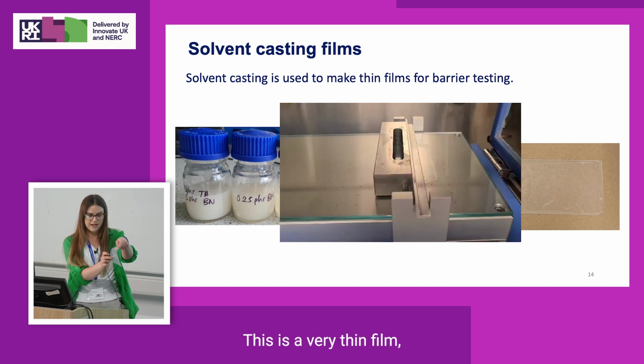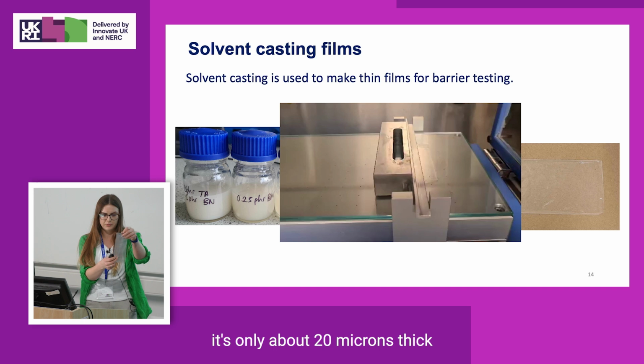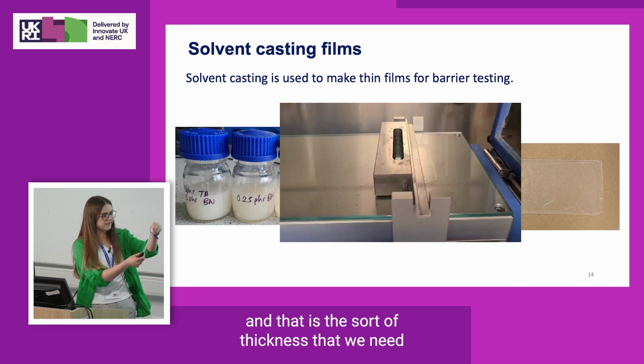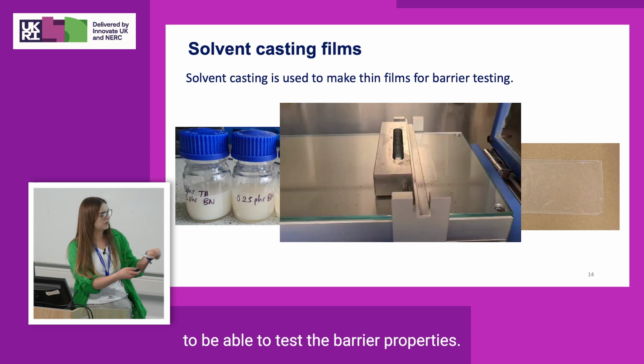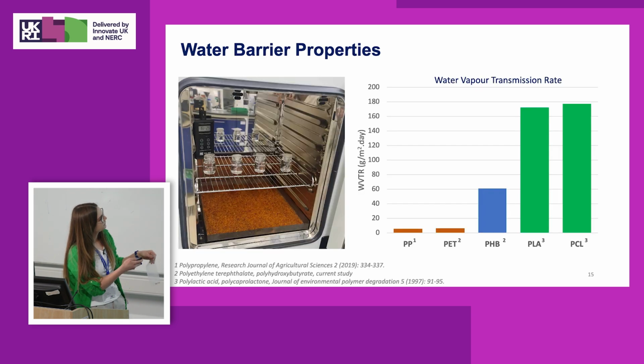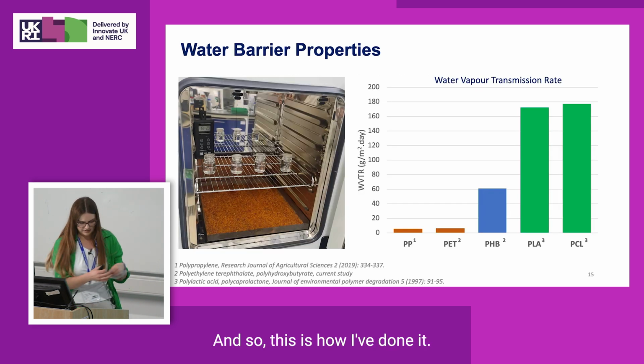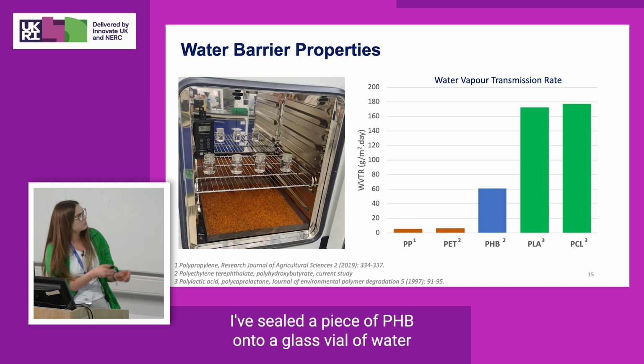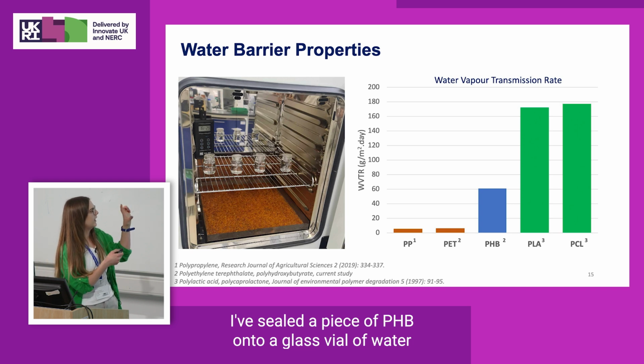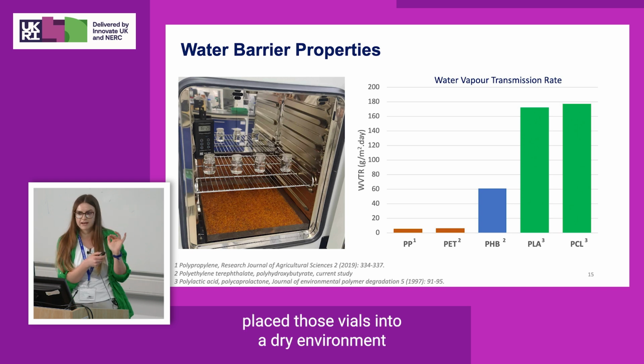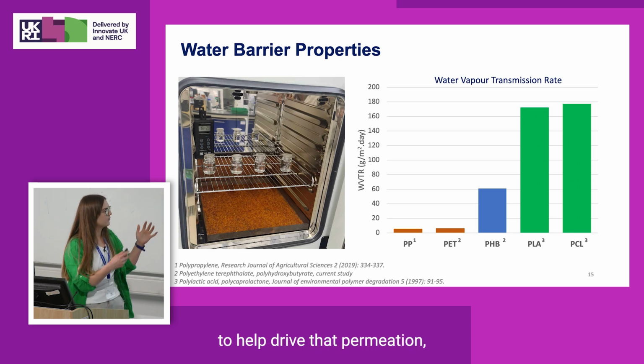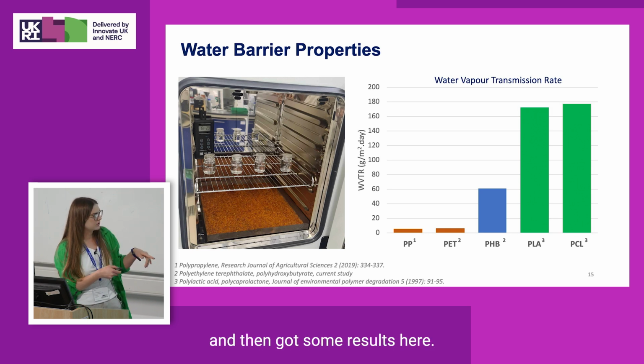This is a very thin film. It's only about 20 microns thick, and that is the sort of thickness that we need to be able to test the barrier properties. And so this is how I've done it. I've sealed a piece of PHB onto a glass vial of water, placed those vials into a dry environment to help drive that permeation. And then got some results here.